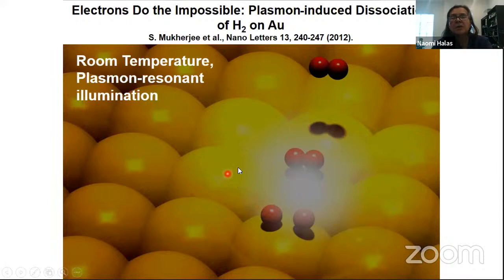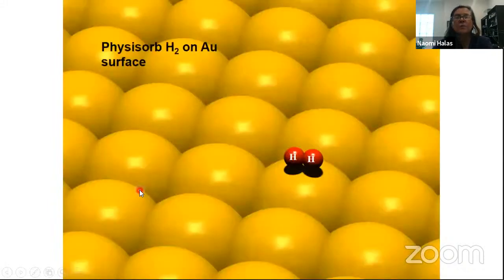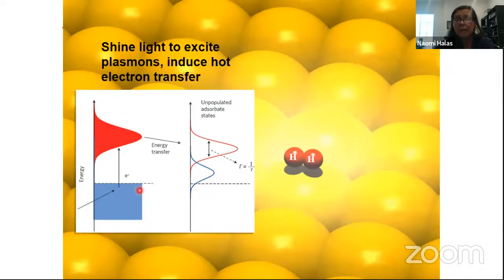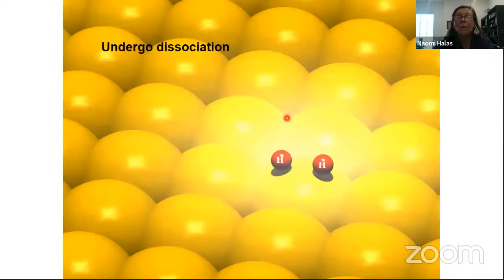And we're going to do this with light that is resonant with the actual plasmon. We're going to excite the plasmon of the nanoparticle. As I said, we flow H2 over the surface. It associates only very, very weakly with the gold surface, just very weakly physisorbs. Then we turn on the light, we excite the plasmon in the gold nanoparticle, and the hot electrons, as that plasmon decays, transfer to the LUMO level of the H2 molecule. So it becomes H2 minus. The barrier to dissociation of H2 minus is much, much lower than the barrier to dissociation of H2. And so we undergo dissociation. It's actually less than an electron volt barrier.